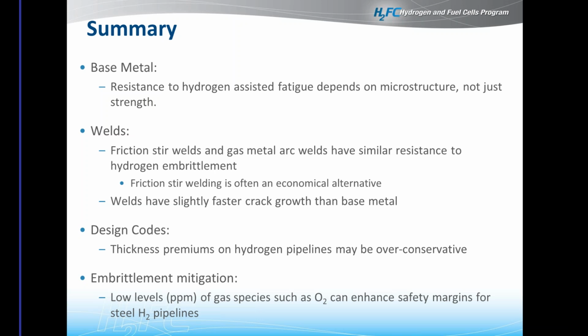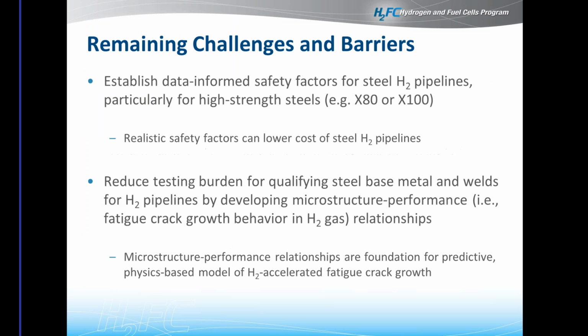And then doing some calculations, actually putting pen to paper and saying, okay, now that we have some experimental data, can we actually calculate what pipeline thicknesses are required to sustain a life of, say, 50 years? We found that given the current natural gas codes, those appear to be conservative enough for what we are looking at. And then finally, just from the kind of tangential study on oxygen effects, we found that low levels of gas species, such as oxygen, could potentially enhance safety margins by this mitigating effect that they have on hydrogen embrittlement.